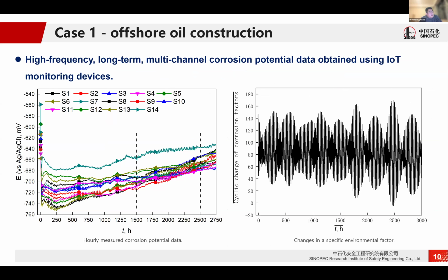Here are the open circuit potentials of 14 materials that we collected in the real environment. This graph on the left shows the open circuit potential, and the test of open circuit potential in the environment has been carried out for a long time, but with the improvement of technology, high frequency, long period, and multi-channel online testing has been realized. This also provides a basis for us to use this data to carry out follow-up work.